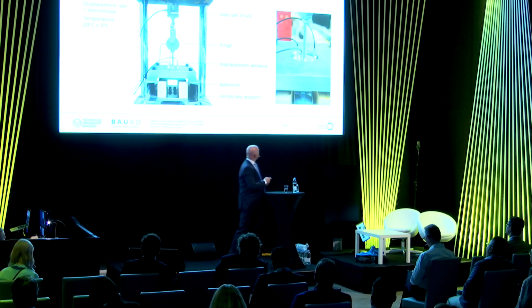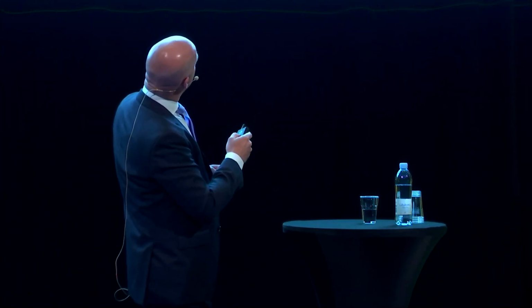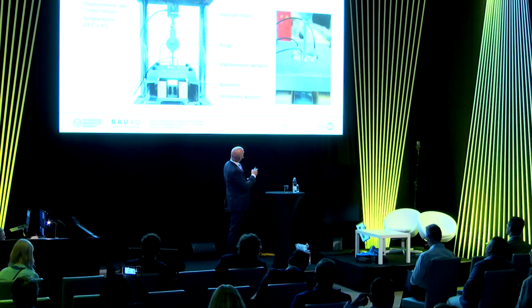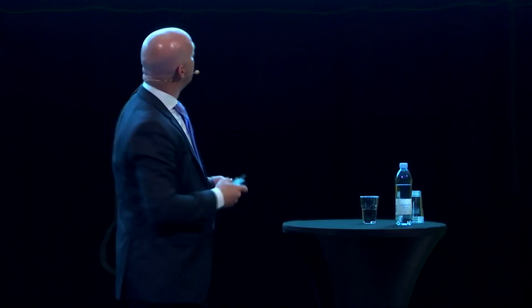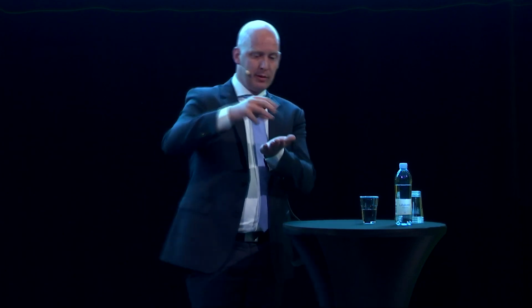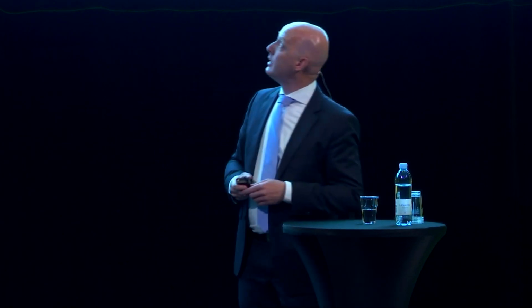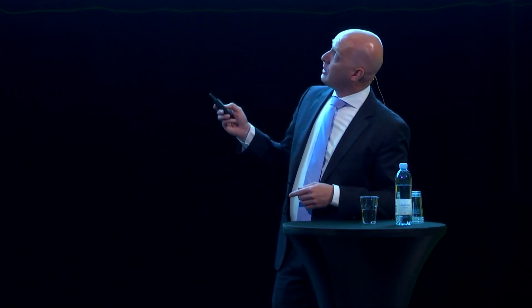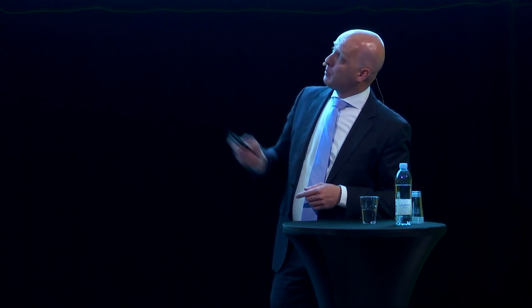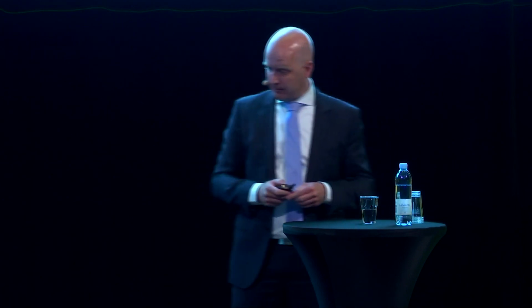What we are measuring, you can see on the other side, with these 3 LVDTs, we are measuring the relative displacement of the bottom compared to the glass again. So we can also measure the inclination there. We do that again at a test speed of 1 millimeter per minute, and again at a non-conditioned temperature of 23 degrees, room temperature.